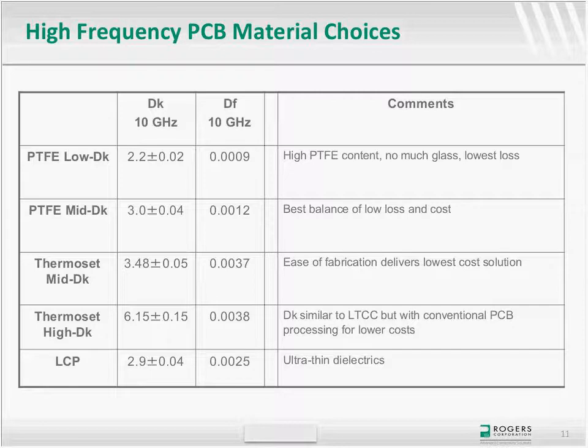You will also see that these materials have much tighter dielectric constant tolerance. Although I will say this: when one is looking at repeatability of the circuit, we find that thickness control is as important as dielectric constant control. So always take that into consideration when looking for repeatability in materials: also look at the thickness tolerance and its impact on impedance variation versus dielectric constant.